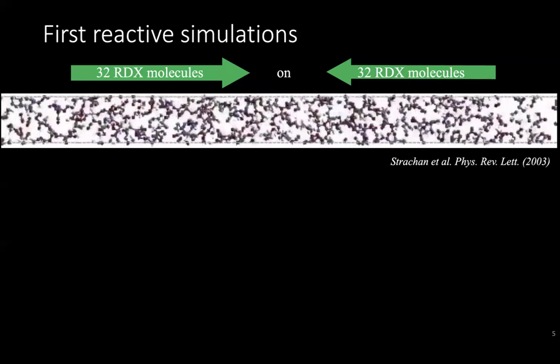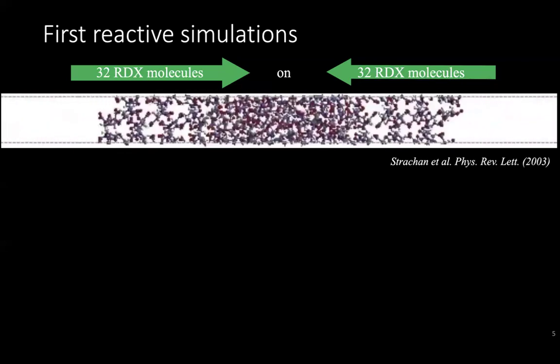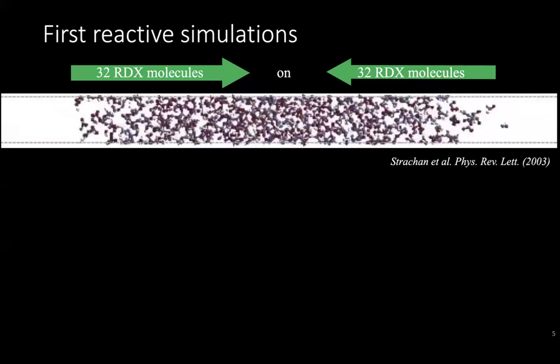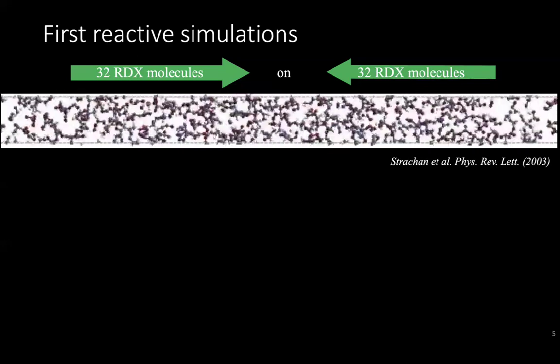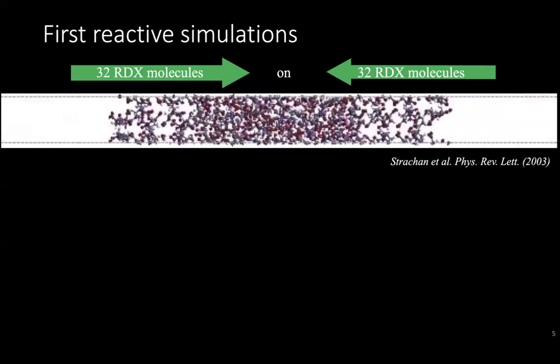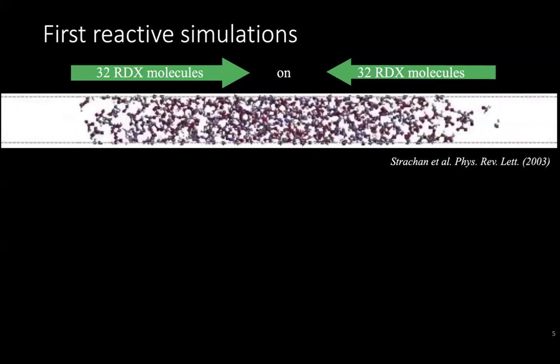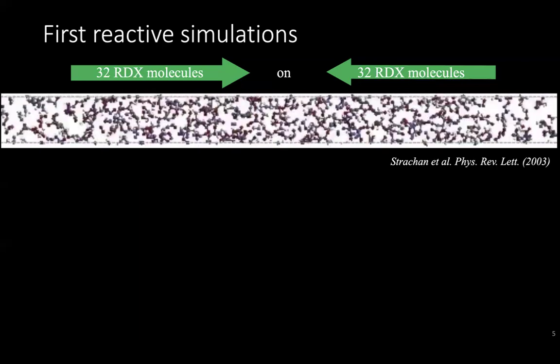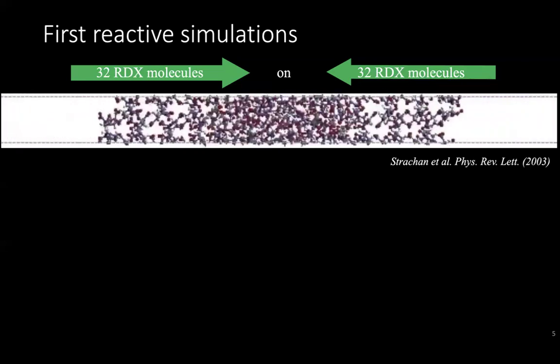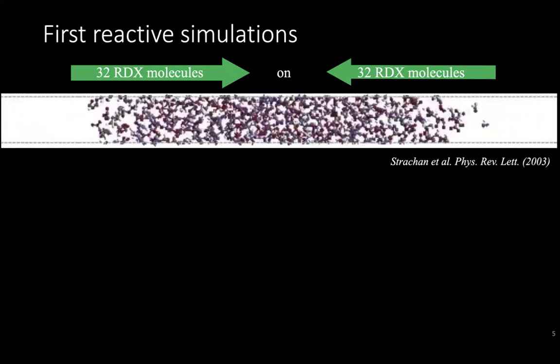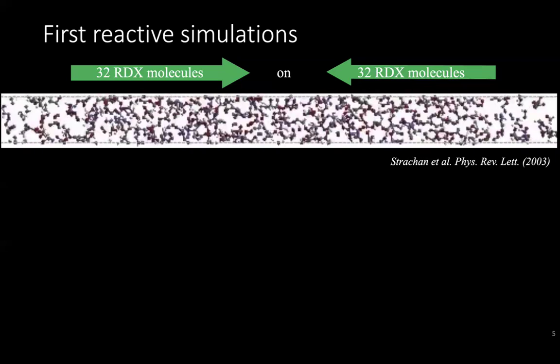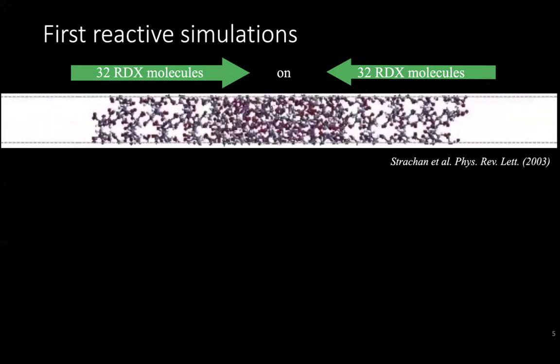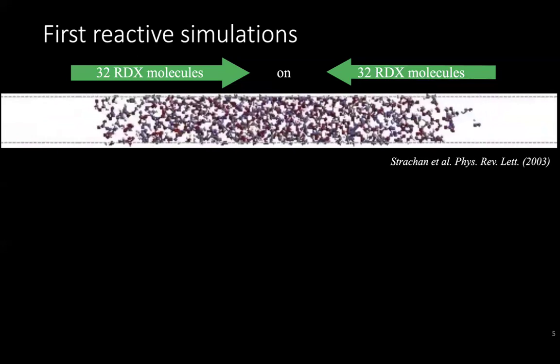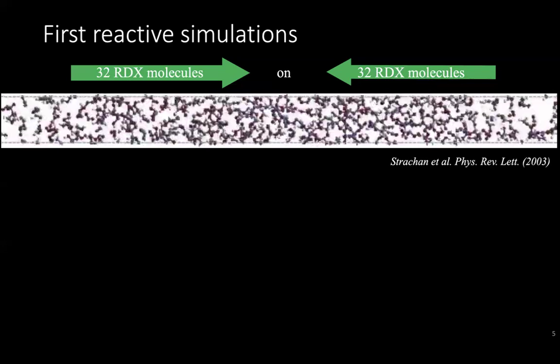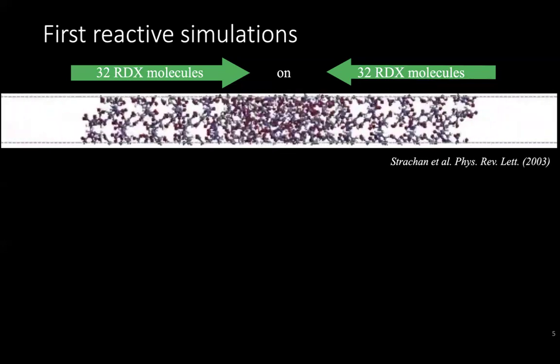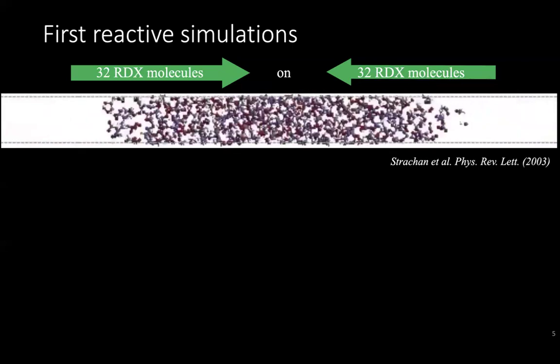And the understanding back then was, well, the shock comes in, it puts in a lot of energy, all of these degrees of freedom thermalize. It's a process called up-pumping. Dana Dlott from here, chemistry, did a lot of work there. And then the system thermalizes to some temperature, and then there's thermal decomposition. I can use regular rates at high temperatures for the decomposition. What we saw is very different, just bonds being broken mechanically.